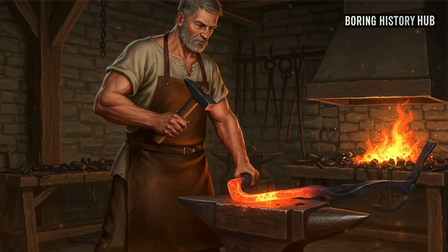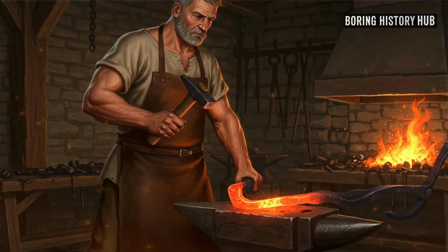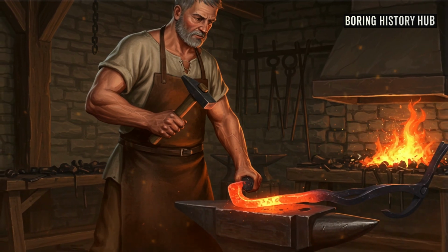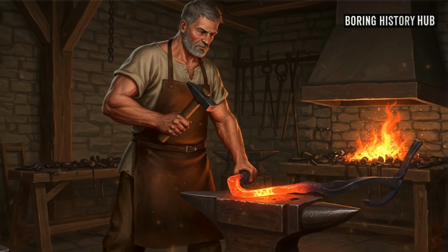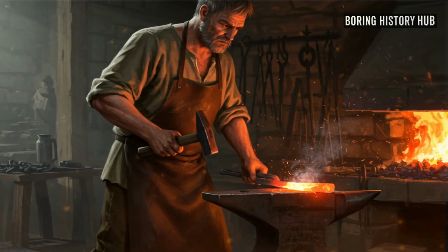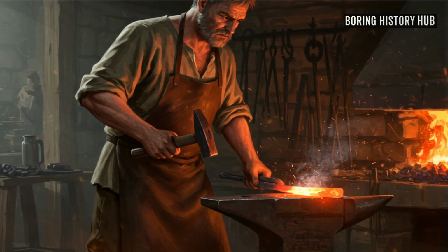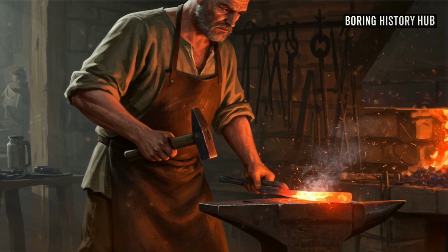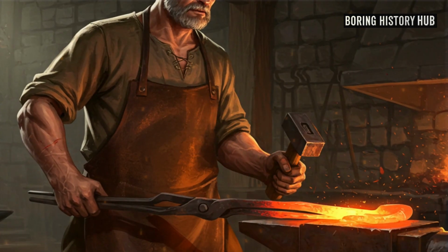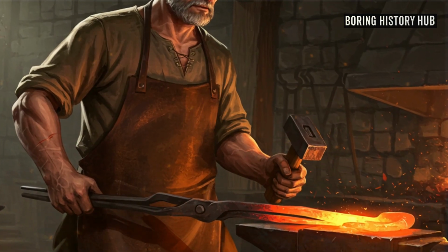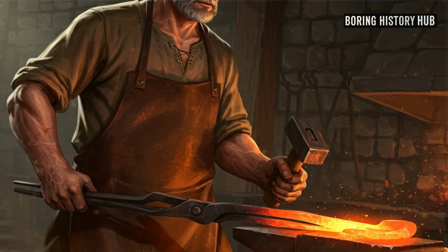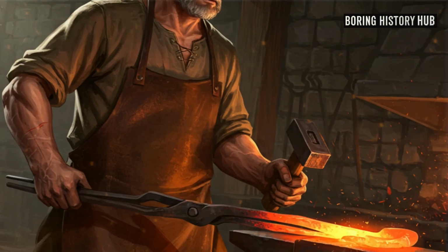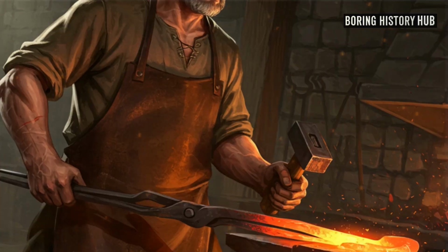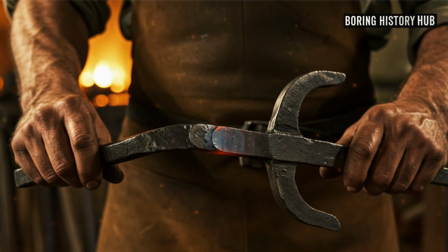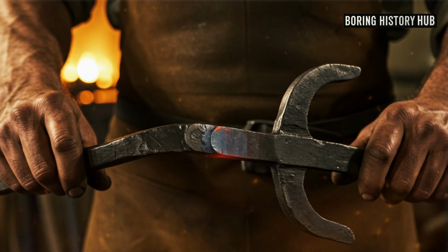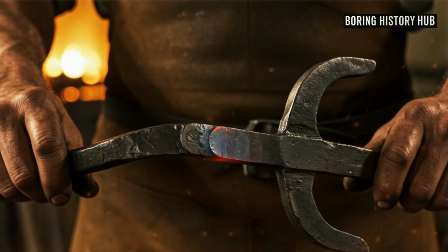The replacement section was forged from new iron stock, carefully shaped to match the original profile of the plowshare's cutting edge. The welding process that would join new and old metal required perfect temperature control and precise timing. Edmund heated both pieces to welding temperature simultaneously, quickly assembled them on the anvil, and hammered the joint closed before either piece could cool below the critical welding heat. The completed weld was nearly invisible, appearing as just a slight line where the new metal joined the old.